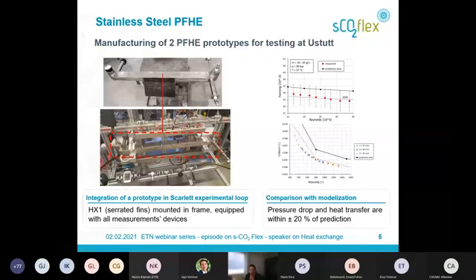So we manufactured during this project 2 types of PFHE prototypes for testing at the University of Stuttgart. So you can see one of these prototypes with serrated fins, and these prototypes mounted in frame and equipped with all these measurement devices. So they performed several measurements in several conditions, and we can see the fanning factor representing the pressure drop versus the Reynolds number, and we are within about 20% of the prediction data. It is the same for the Colburn factor representing the heat transfer coefficient versus the Reynolds number. It's quite the same situation. The prediction is really good compared with the modelizations.